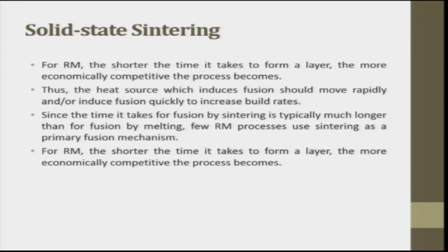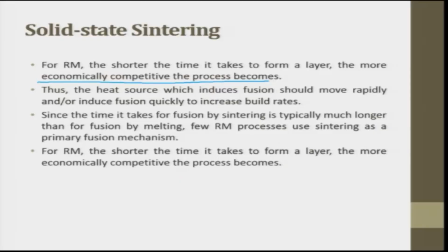For RM, the shorter the time it takes to form a layer, the more economically competitive the process becomes. So, you have to use only smaller particle size. If you use a larger particle size, the driving force will be less, so you will have to apply more heat, and when you apply more heat, it takes longer to make the parts. Thus, the heat source which induces fusion should move rapidly or induce fusion quickly to increase the building rate.